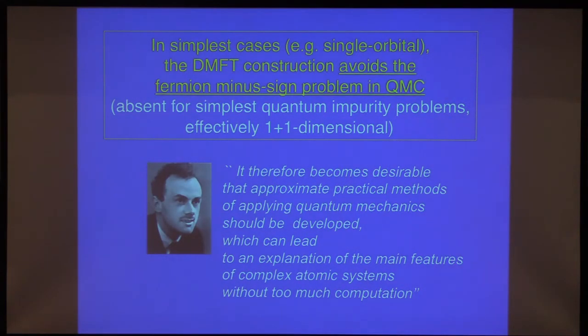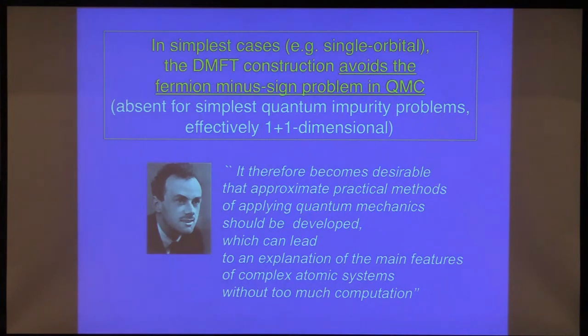To a certain extent, this is a step towards the program of Dirac, because we've managed to bring this formidable problem of computing 10 to the 23 electrons interacting together into a problem, with some approximation, which becomes manageable. The reason it becomes manageable is that this local problem of one atomic shell coupled to a bath, if you treat it by a Monte Carlo algorithm, for example, is free of the minus sign problems I was describing before, and you can really solve this problem on the computer very accurately.